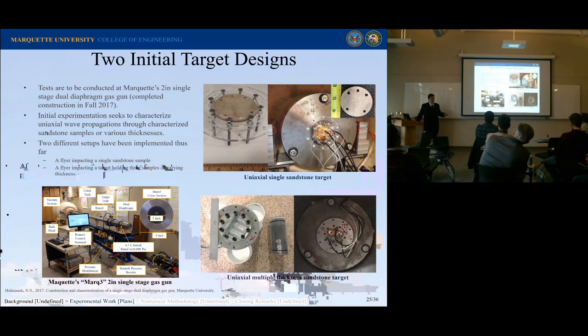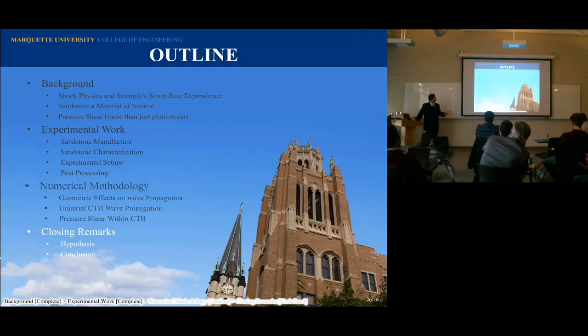So I have two initial target designs, and I'm going to shoot them in our Mark III single-stage gas gun. We have this single uniaxial sandstone target. We just hit the face, and then the other target that we have is a three-sample one, so we can monitor the effect that grain sample thickness has, and figure out what the minimum thickness is that we can use for a heterogeneous sample.